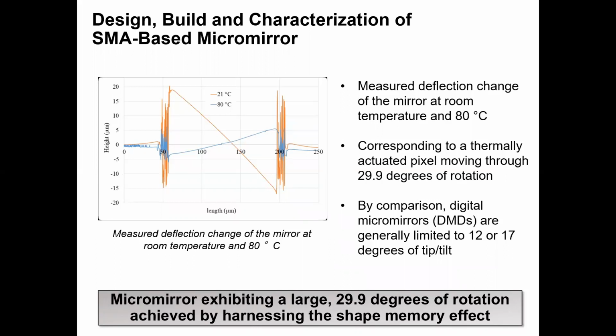So this device actuated from a starting angle of a positive 23.3 degrees. It went through flat, or 0 degrees, down to a maximum tilt of negative 6.6 degrees. And this corresponded to a total tilt angle change of 29.9 degrees. And this is relatively large compared to typical digital micromirror devices, where deflection is usually limited to around 12 degrees of tip tilt.